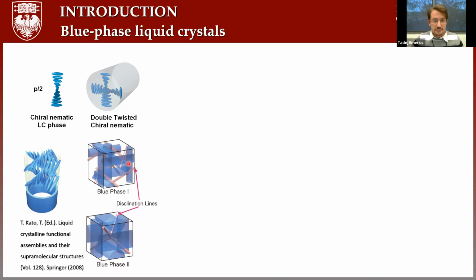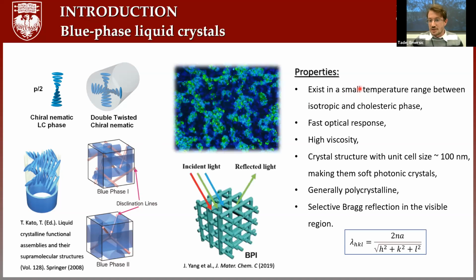So about the blue phase, we know that it exists in a very narrow temperature range between the chiral nematic phase and the isotropic phase. So here we are talking about 1 or 2 or 3 degrees C. Blue phases have fast optical response and high viscosity. As I mentioned, they form a crystalline structure with a unit cell size that is pretty close to the visible light wavelength, so around 100 nanometers. And that makes them like soft photonic crystals.